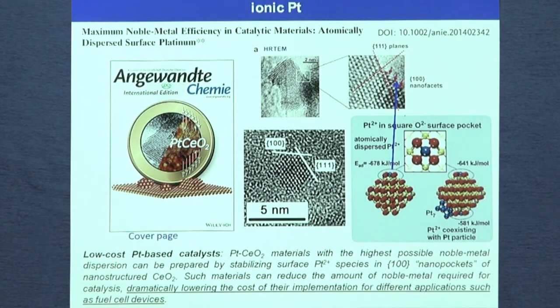And the stability of these atomically separated atoms is higher than the stability of metallic platinum, and the platinum is not sintering. This is something which is now quite popular, called a single atom catalyst.